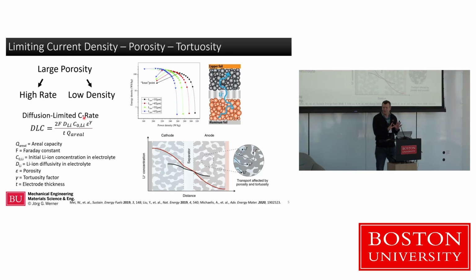That's pretty slow for batteries, so 0.1 C is usually kind of our baseline. That's where we don't have issues with that mass transfer. 1 C, 2 C, 3 C, that's where we get really fast, right, sub-hour charging, where we're interested in. And what this equation essentially shows is that, of course, the diffusion coefficient of lithium, how fast it can move through the electrolyte, matters. The faster it can go, the faster you can charge your battery. The concentration of lithium ions in your electrolyte is important, though that's limited often by solubility, and has sometimes at the very high concentrations a negative effect on the diffusivity.